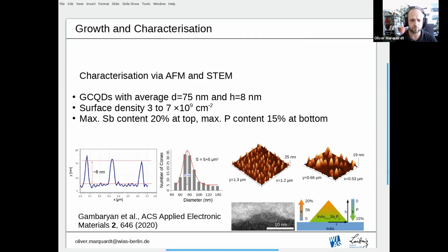We could estimate the surface density to be 3 to 7 times 10^9 per square centimeter. And we would expect, as I said, a composition gradient, as you can see down here, with a maximum antimonide content of 20% at the top of the systems, and the maximum of the phosphide content here at the bottom of about 15%.